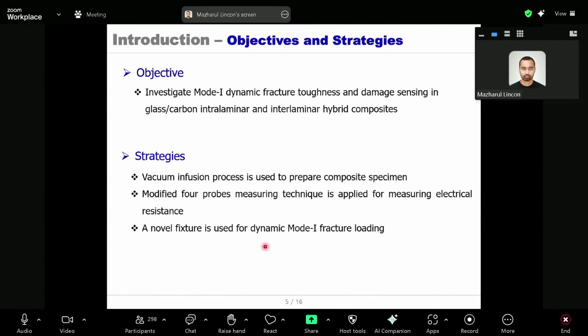The strategy we followed is: a vacuum infusion process is used to prepare the composite specimen, a modified four-probe measuring technique is applied to measure the electrical resistivity of the specimen, and a novel fixture is used for dynamic mode-I fracture loading.